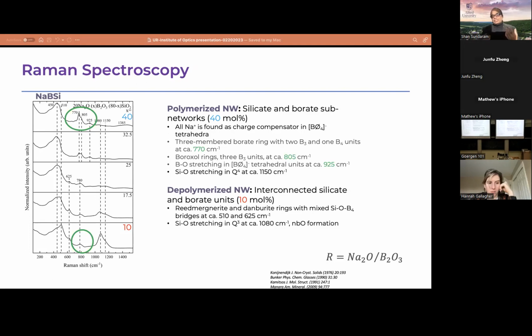Now, I'm giving you just an example of Raman spectroscopy data. Raman also activates a specific bond of specific members in the glass structure. You can see here again for 40 mole% polymerized borosilicate glass, all the sodium is affiliated to boron tetrahedra. In this case, the 770 centimeter inverse bond corresponds to the 3-membered borate ring, B3 ring, and 1 B4 tetrahedra unit. That's the response you are getting at around 770 centimeter inverse.